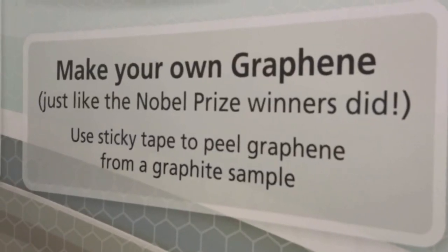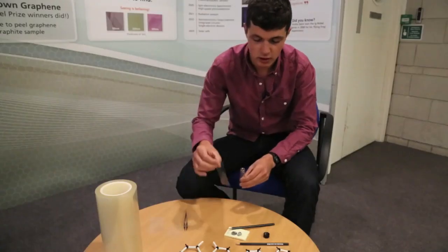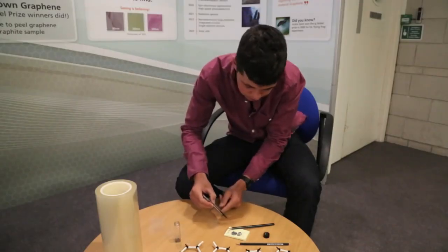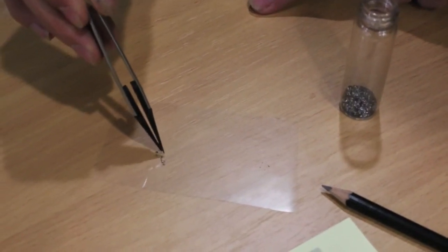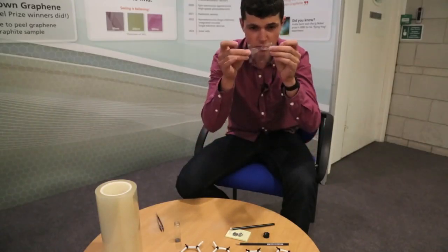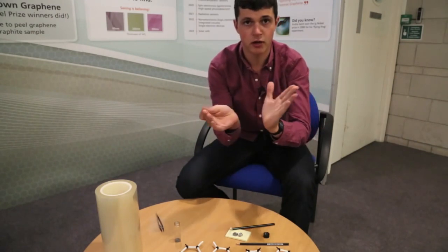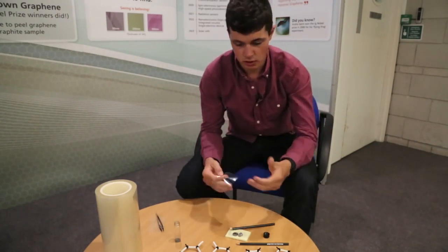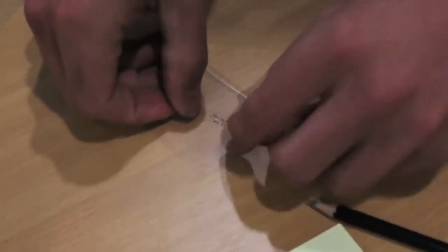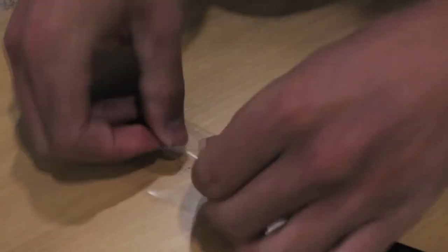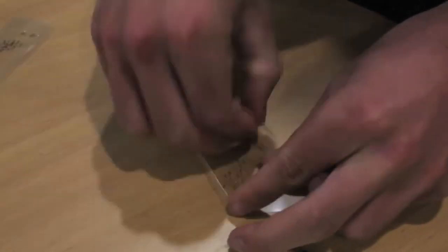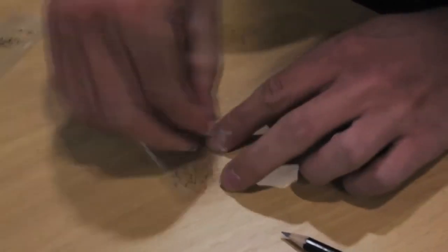It's actually surprisingly simple. You need to use a simple piece of sticky tape, and we use the tape to pull the layers of graphite apart. And every time we pull the tape apart, we break our graphite up. We're cleaving it, pulling apart the layers. So the pieces of graphite we had in here originally would have contained many thousands of layers. And if we do this enough times, we can hopefully end up with some layers that are only one or two atoms thick.